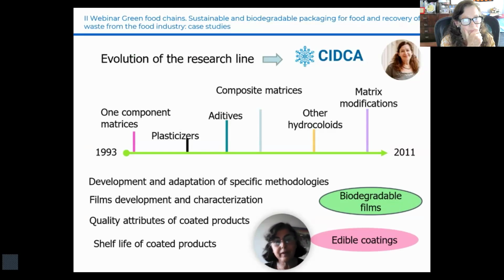We began by developing edible coating for extending the shelf life of strawberries based on cornstarch. We studied the effect of adding glycerin and sorbitol as plasticizers, as well as the use of potassium sorbate as antimicrobial agent in the formulation. We developed and characterized films adapting specific methodologies for synthetic materials. In the case of the coating, we studied the quality attributes that determine the shelf life of the fruit. During my postdoctoral fellowship, we began studying coatings and films based on other hydrocolloids, such as cellulose derivative, chitosan, and kefiran.